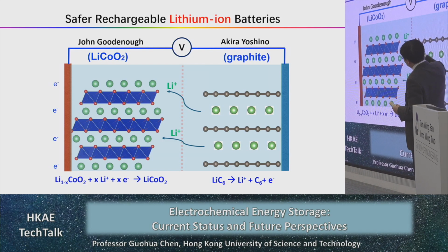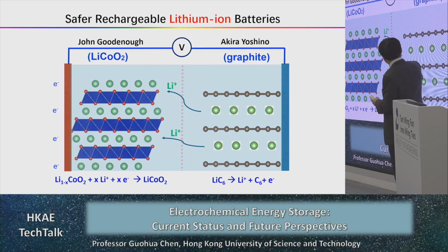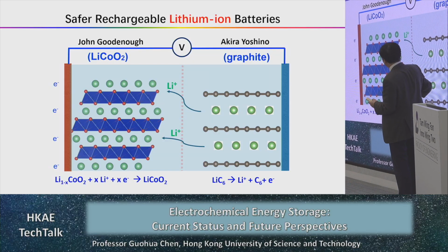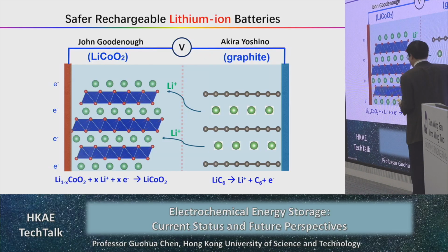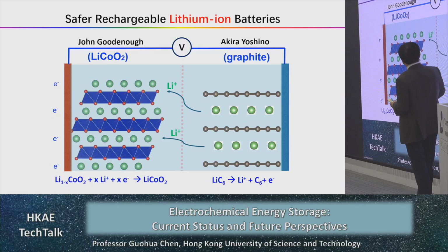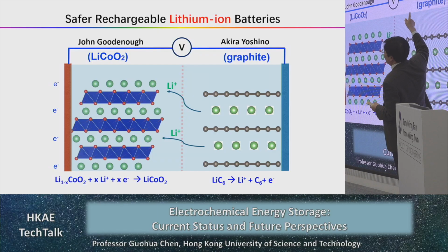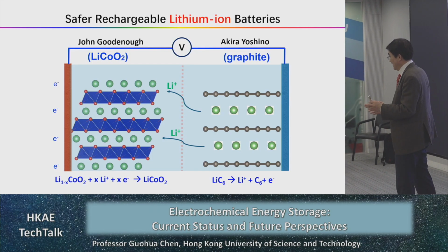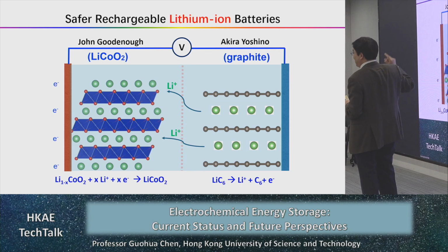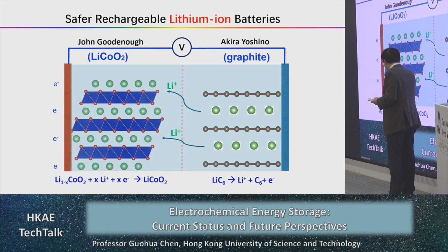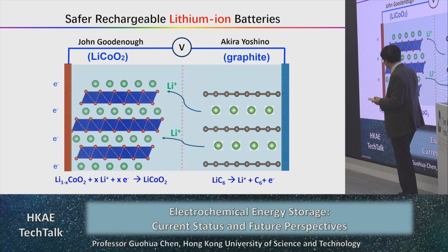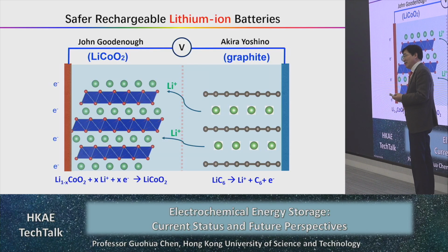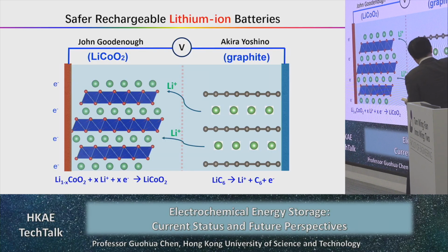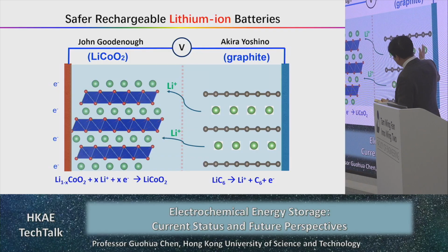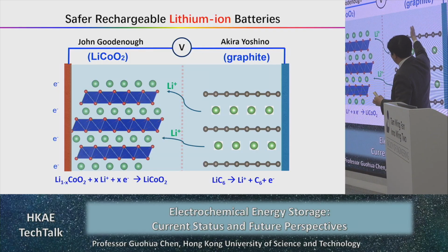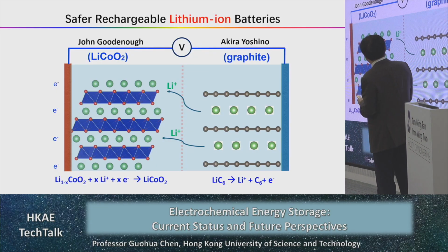And this makes the battery much safer, because if you look carefully in the electrolyte, you only see lithium ion. And here you do not have lithium metal. There, of course, you do not have lithium metal. So this kind of battery we call lithium ion battery. So now, the batteries we are using all are in this form, lithium ion battery. And the difference is whether or not they use cobalt oxide or manganese or NMC or lithium iron phosphate, things like that. Or on this side, they could use some other type, silica or silicon or special kind of structure for lithium insertion, okay?